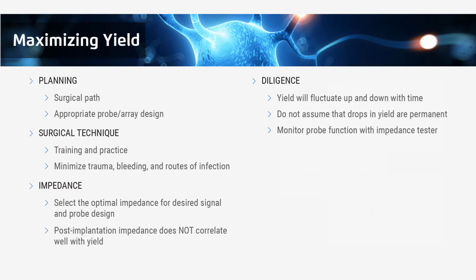Something that's important to note is that post-implantation impedance does not correlate well with yield. Impedance of an implanted array will fluctuate quite a bit as the inflammatory process progresses. It typically follows a fairly consistent progression within the first 2 weeks, but after that you will see impedance fluctuate a good bit. However, it has been shown that this does not really correlate with yield. However, impedance can be useful.